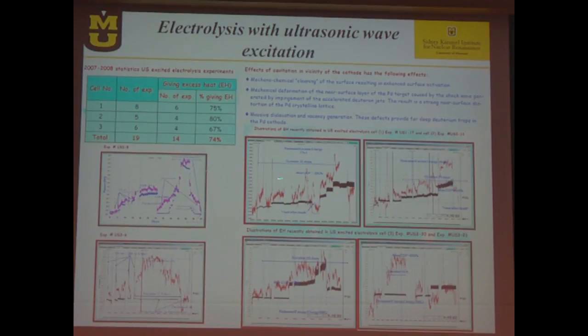Second thing, by using this method, the duration of generation of excess heat is much longer than in regular electrochemical cells. And last but not least, and we'll see it immediately, the natural deloading of deuterium from the lattice is much lower than in any other electrochemical cell, and we believe it is due to the formation on the surface of the cathode due to this plastic deformation. But if you look at these, here we have up to 3,000% excess heat. Here we have 200 and 500 and 600, and the durations are days, 23 days, 12 days, and so on. Very long processes, much longer than in any electrochemical regular cell which is not excited by ultrasound.